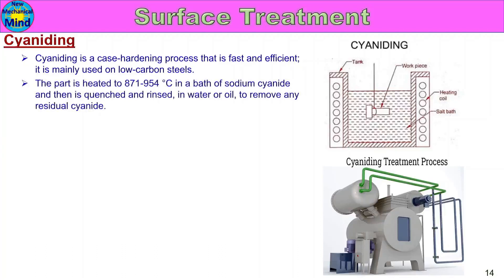The part is heated to 871 to 954 degrees centigrade, and then quenched and rinsed in water or oil to remove any residual cyanide.